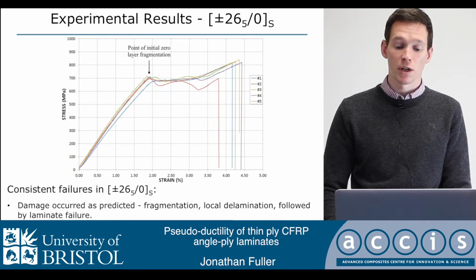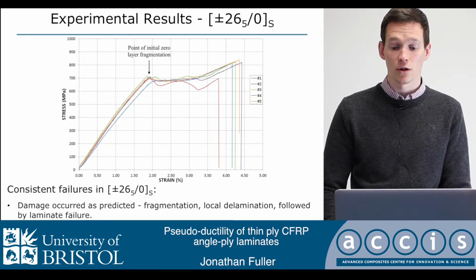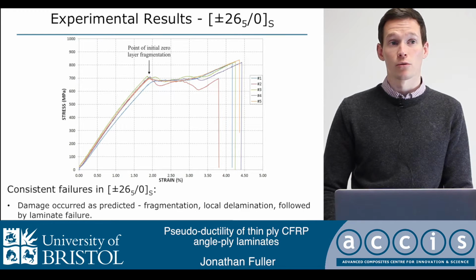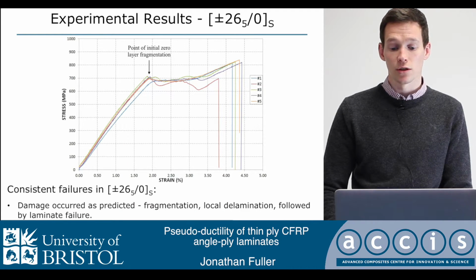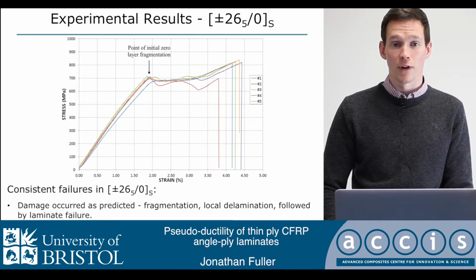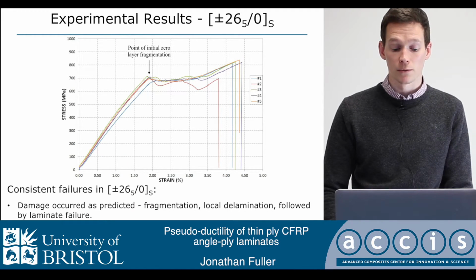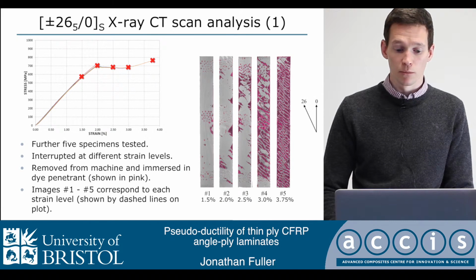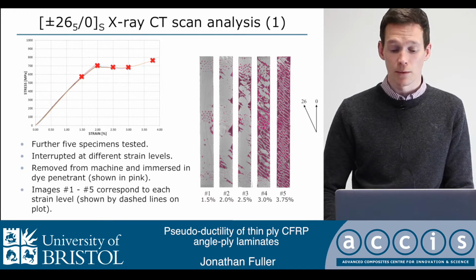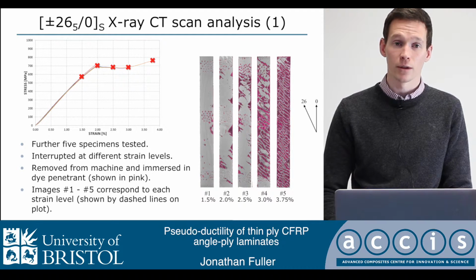This further loading takes place after fragmentation and delamination of the zeros, and then the angle-plies, which remain relatively undamaged, continue to take the load up to a failure which is similar to the value of the angle-plies by themselves. So obviously, how do we know what damage is in the specimen? It's key to know that and how it develops.